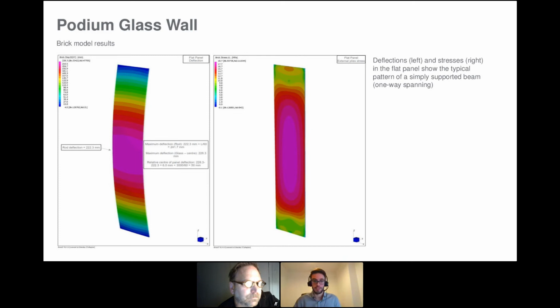And we had to analyze clearly not only the flat panel, but also the curved one. But this analysis also highlighted even more the behavior that we were expecting, and that I was mentioning before. So for what concerns the flat panels, we basically can see a very typical one-way spanning behavior. So as a simply supported beam spanning between rod and rod, with clearly some slight help coming from top and bottom shoe in order to reduce the stress. But basically you can see that the shape of the stress is almost similar to the one if I was just taking a slice of the panel and assuming it was a simply supported beam spanning from rod to rod.